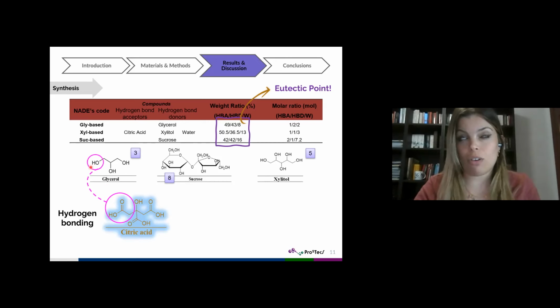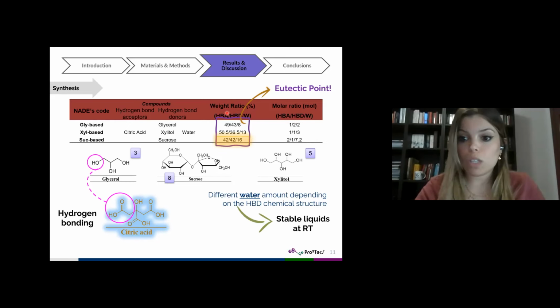in the table. Moreover, for this formulation, as previously detailed, the addition of water is required to obtain this stable mixture forming a supramolecular structure, needing a greater amount of water as the number of hydroxyl groups forming the hydrogen bond donor compound was raised. I mean, in the sucrose-based sample, we need a higher amount of water than the other ones.